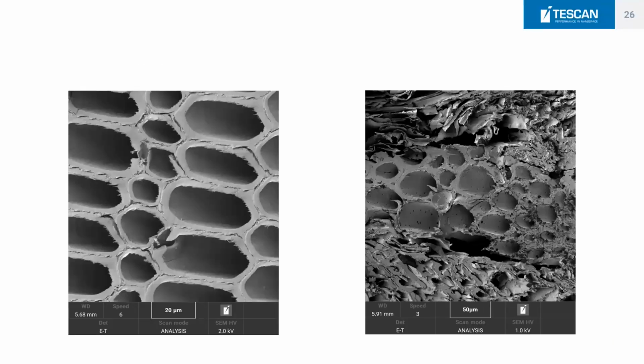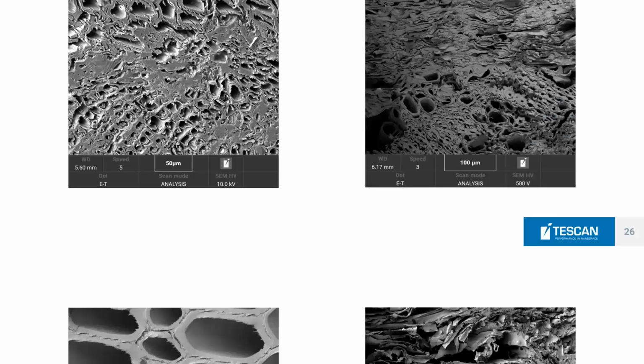You can zoom in on a specific part, and on the left-hand side, you can see a typical structure of wood, and you don't see a lot of delamination, for example. You can see all the cell walls pretty clearly. On the right-hand side, you can see that the cell walls are way thinner, therefore they can break easily, and that the porosity is way bigger. That is one of the key morphology aspects which may affect the mechanical properties of the material, so the material structure itself.